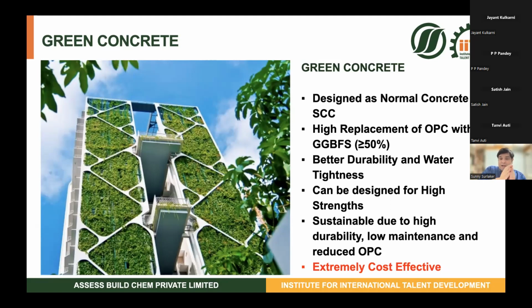But what we were targeting in the mix was a very high replacement of OPC with GGBFS, ground granulated blast furnace slag. What we came across is that this kind of mix had much better durability and water tightness as opposed to conventional mixes. We could design this kind of mix, despite the low OPC contents, for very good strengths. I wouldn't say very high strengths, but very good strengths.